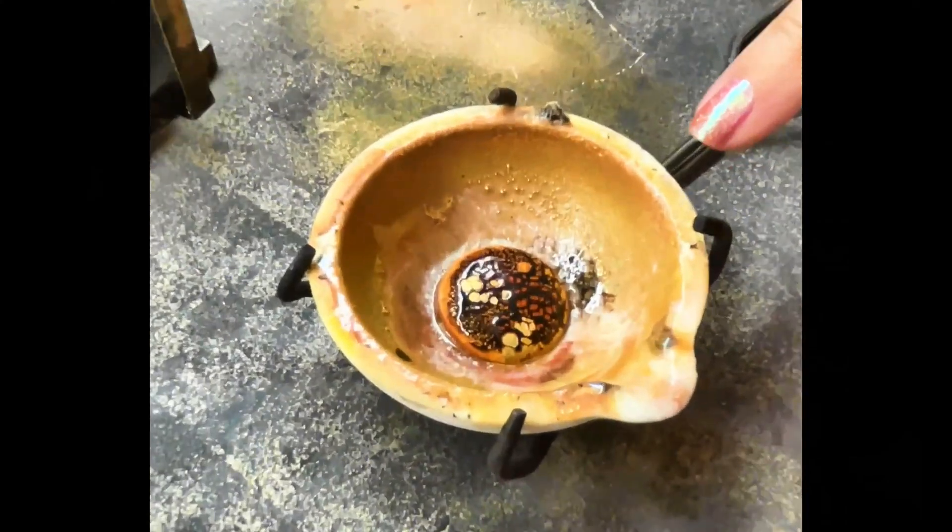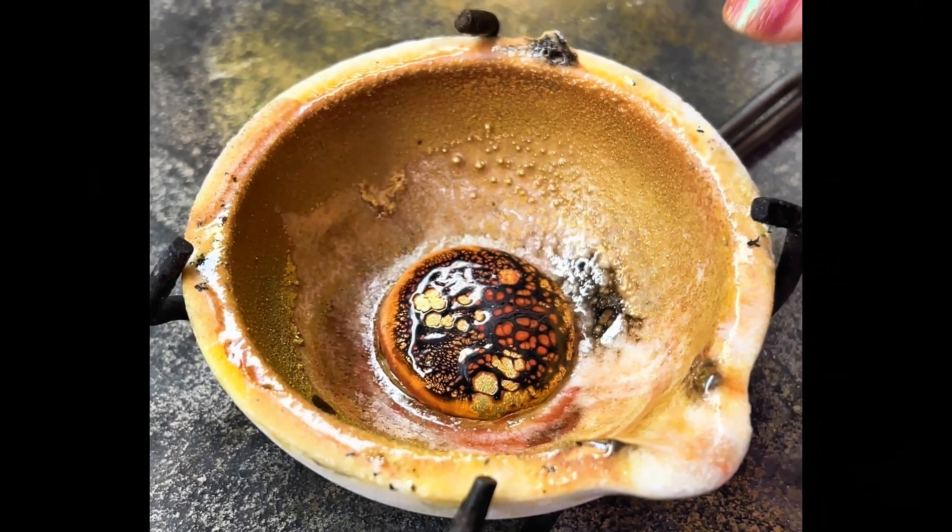If this forms enough of a puddle over it, it's like you can't get it hot anymore. The borax becomes this sort of insulating dome and your gold won't get hot. Basically we were jiggling it and jiggling and nothing. So it's one of those things — how will I know? I promise you, you will know because you'll be like, what the fuck, I can't get my gold hot anymore. And it just sits there like a little stinker. You can see it's pretty much completely covered — maybe not every molecule, but just enough that it forms this — I don't even know the word for it — it's like a snow globe for your gold. Then the heat will not get through it enough to get it liquid.